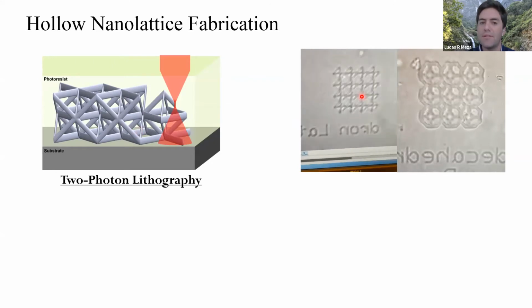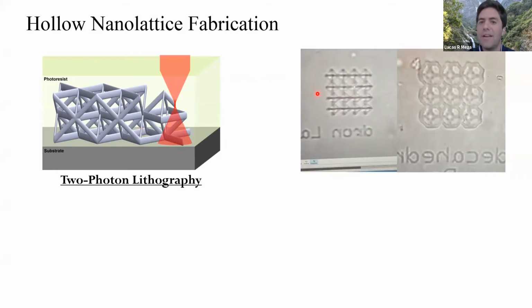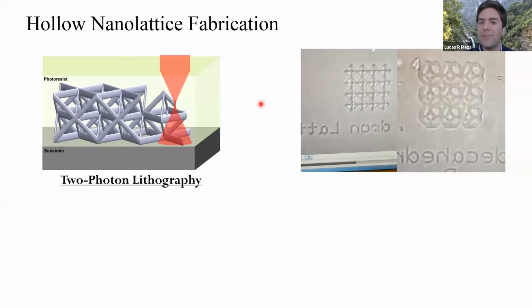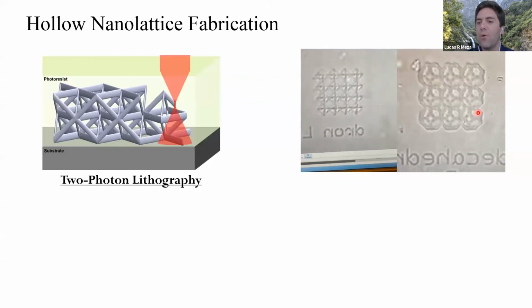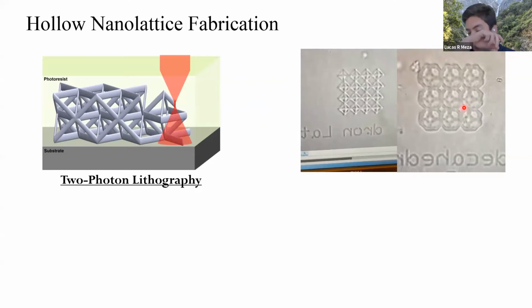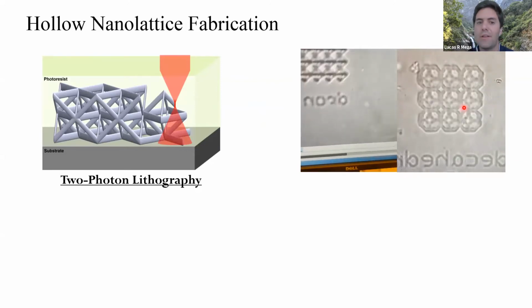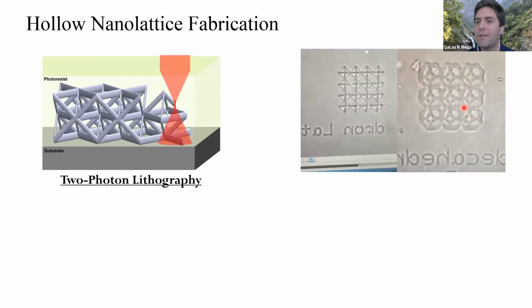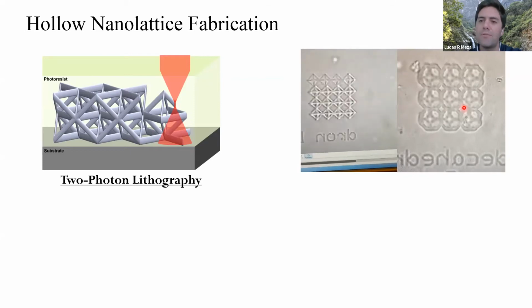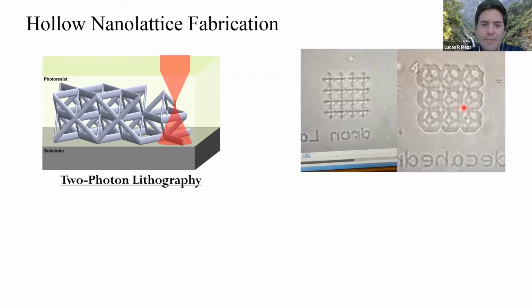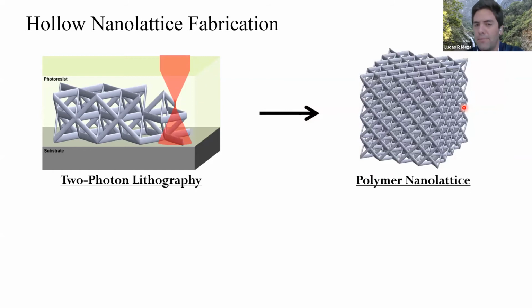You can see there's a piezo stage that this is attached to, and it's writing these octahedrons fully in space. Or you can do layer by layer writing, which is generally faster, but then you get the stair-stepping problem that you get with most 3D printers. At the end of this, you end up with a photopolymer, or polymer structure.